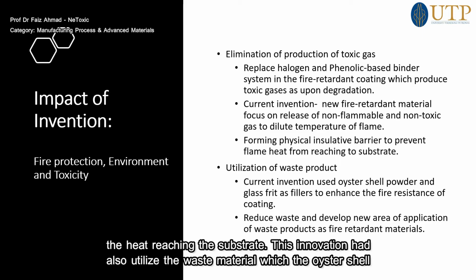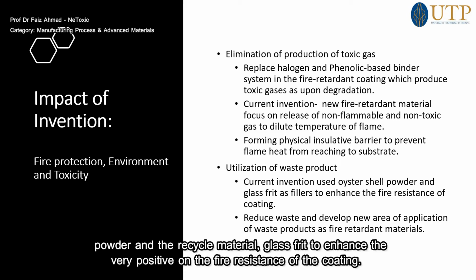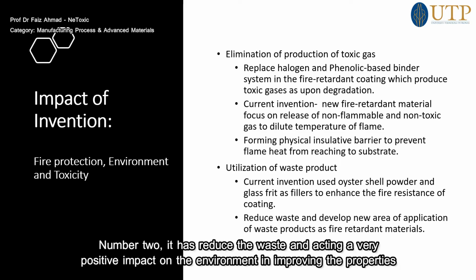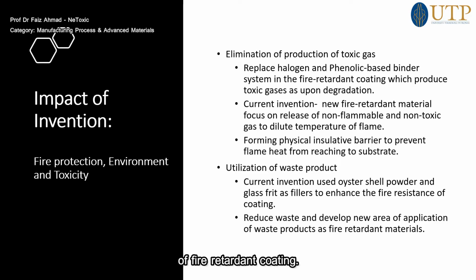to prevent the heat reaching the substrate. This innovation has also utilized waste material, which is oyster shell powder, and a recycled material, glass frit, to enhance a very positive purpose, which is the fire resistance of the coating. And number two, it has reduced waste, having a very positive effect on the environment and improving the properties of the fire retardant coating.